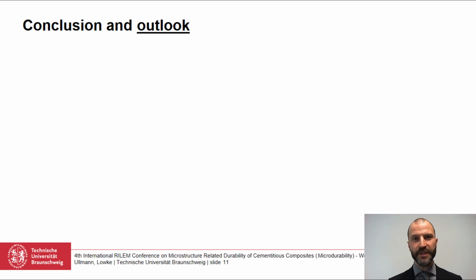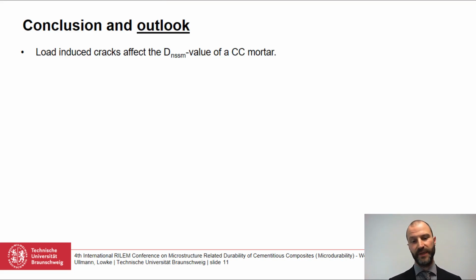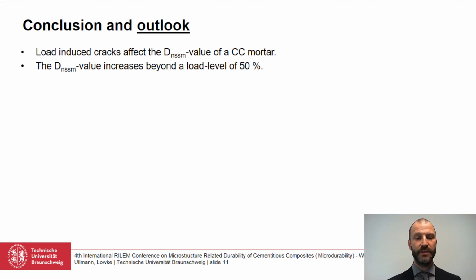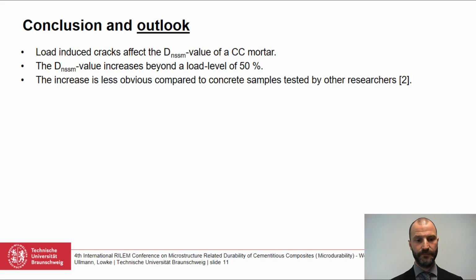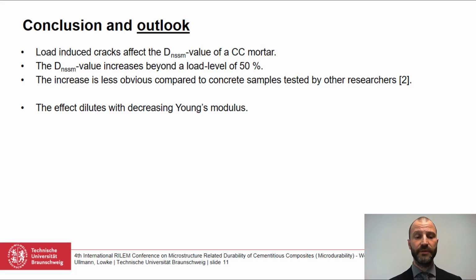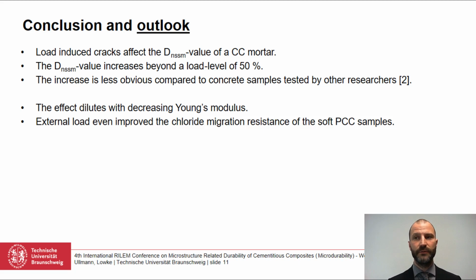To conclude, referring to our investigations, load-induced cracks do affect the non-steady state chloride migration coefficient of a CC mortar. And we noticed that the value increases beyond a load level of around 50% only. That was also noticed by other researchers, and other researchers did the same work on concrete samples. When we compare these results with our results, we can see that the increase that we noticed is less obvious than the ones that were noticed on concrete samples. Generally, we saw that the effect of an increasing non-steady state chloride migration coefficient dilutes with a decreasing Young's modulus. And from our results, we could also say that external load even improved the chloride migration resistance of the soft PCC samples.